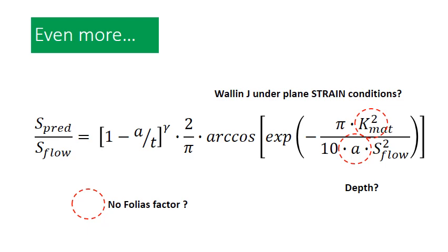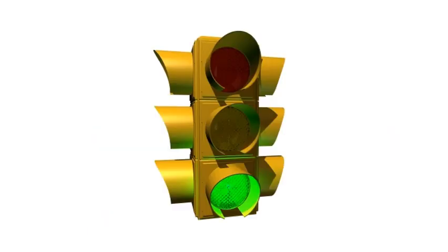If you think about the crack tip that's partway through the wall of the pipe, it's not going to be able to strain in that axial direction in order to increase plasticity and give any apparent toughness. And I've switched out the crack length for a crack depth. So with all three of those issues fixed, I'm giving myself the green light. Feel free to disagree with that, but that's where I am right now.